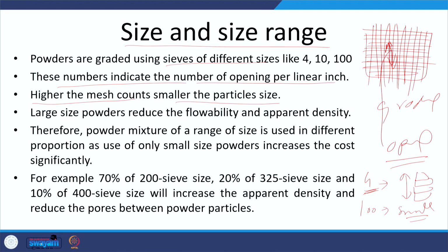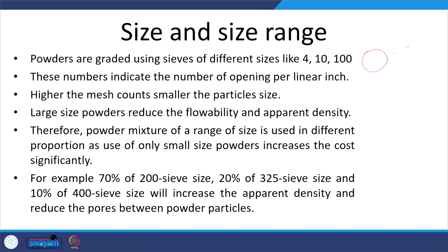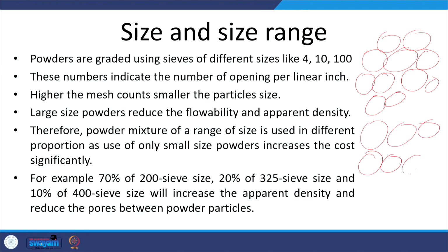Therefore, if we use powders of one size, the chances of having a large gap between the powder particles will be more as compared to the case when we use powder particles of different sizes: few coarse, few fine, few small, few big, few medium.